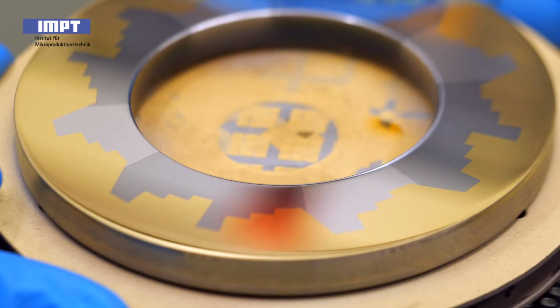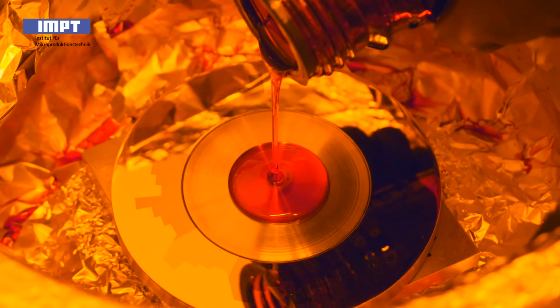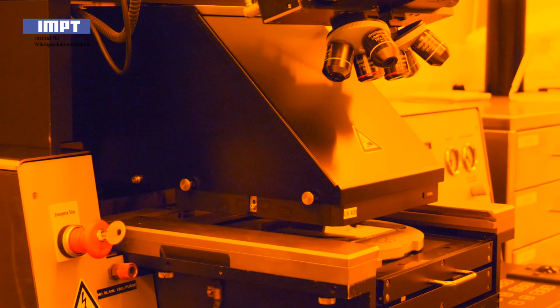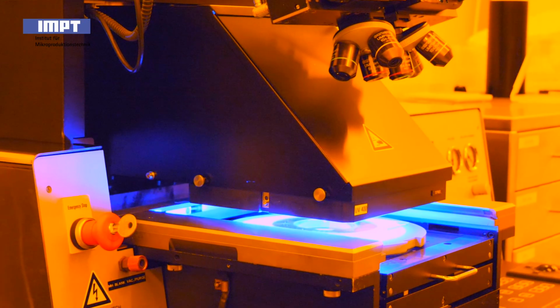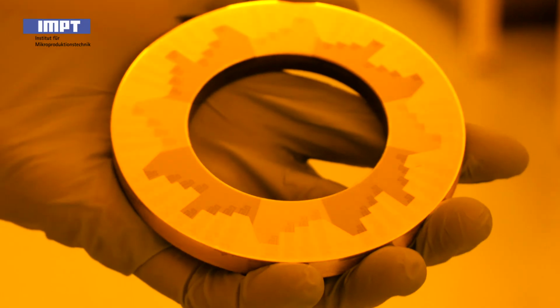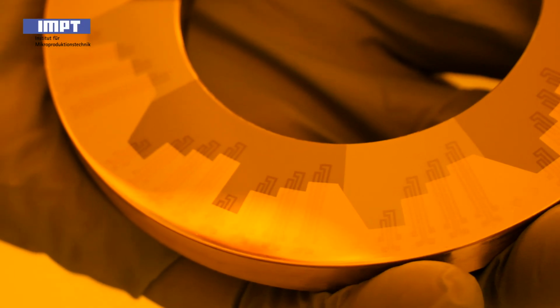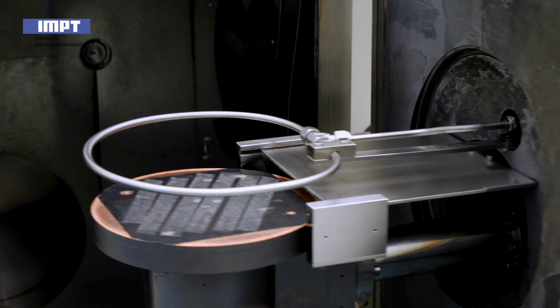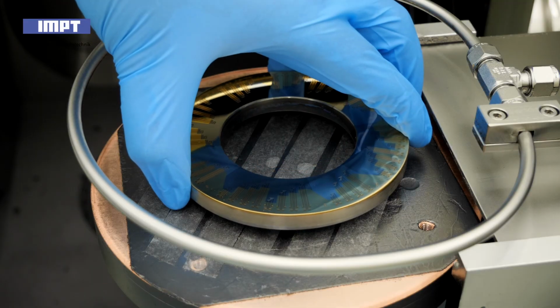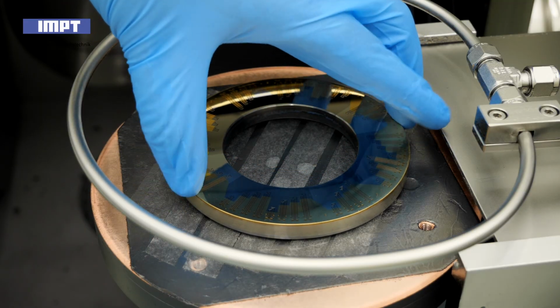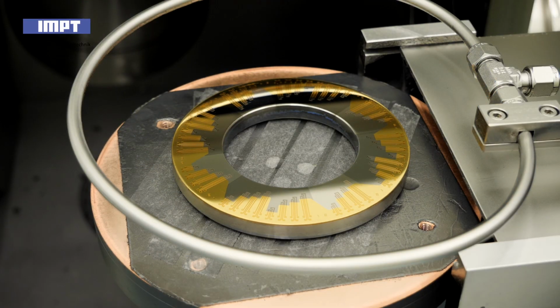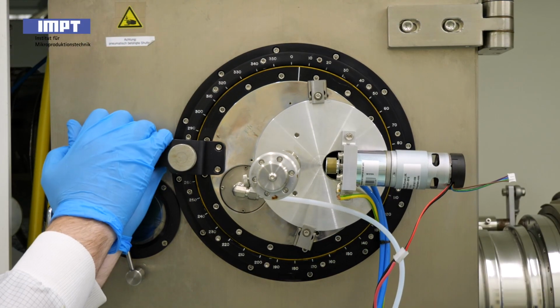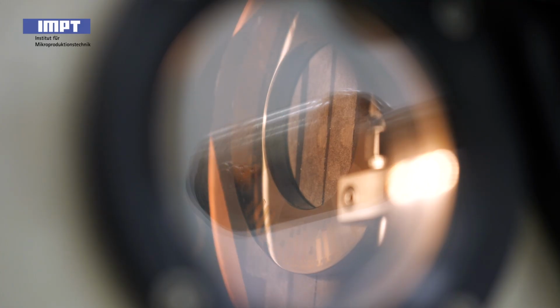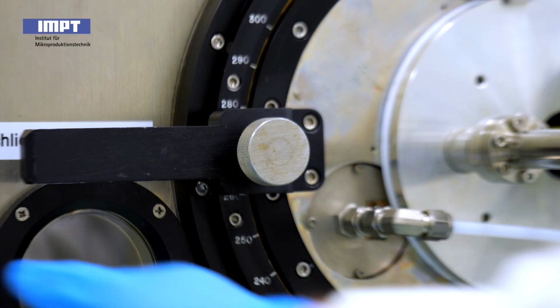Then, the sensor layers are structured. Using photolithography in the yellow light area in the cleanroom, a photoresist is applied and then exposed. After development, only the sensor structures are covered with the photoresist. In the subsequent ion beam etching step, the areas not protected by the photoresist are completely removed down to the insulation layer, leaving only the desired sensor structures on the bearing washer. It is a major advantage of the developed process chain that the etching process structures all layers simultaneously, since it simplifies photolithography on the complex substrate.